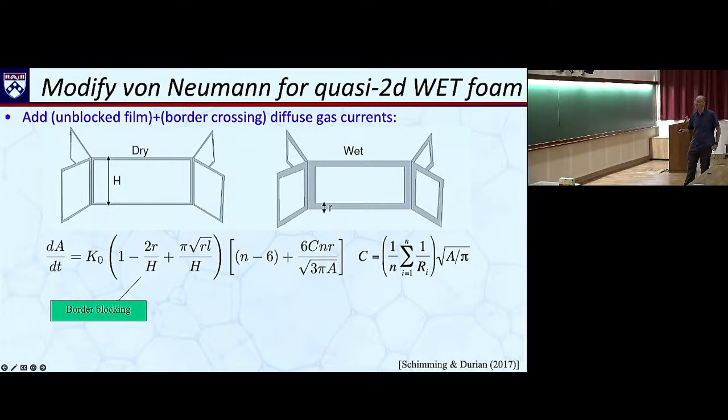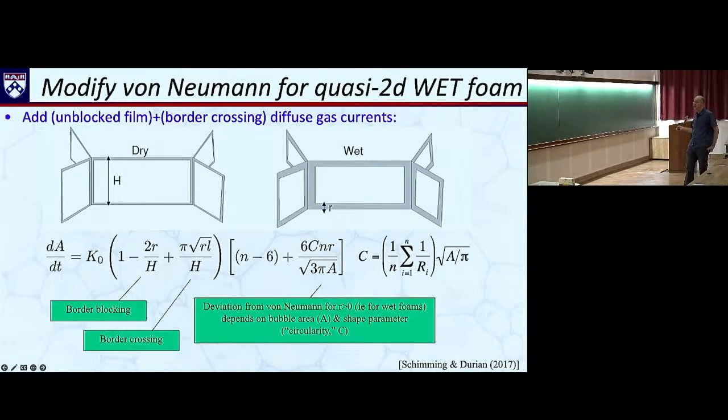This one says that something else comes into play, and this is what we call a shape factor. It's a geometrical shape factor. It's something that quantifies the shapes of the bubbles. So the square root of area, if you were to divide this by perimeter, you'd get what people might call compactivity or elongation, something like that. You can normalize it to be 1 for a circle. But look at this. We're not going to divide by perimeter. We're going to divide it by the average curvature of all the bubbles, the arithmetic average curvature. It doesn't matter how long they are. We're just going to include each one the same.